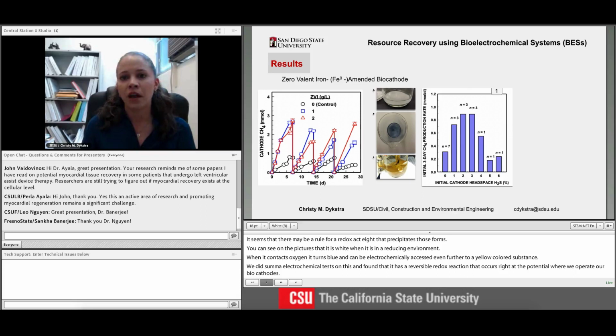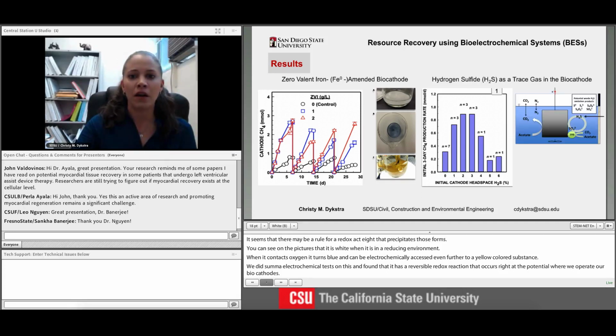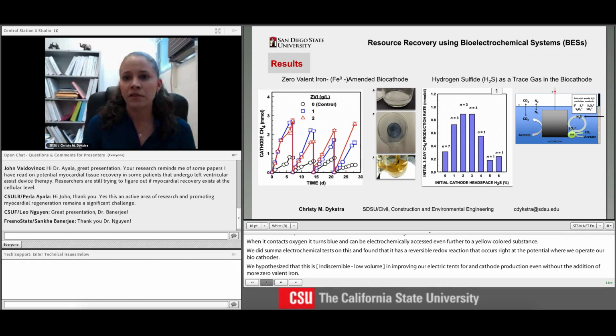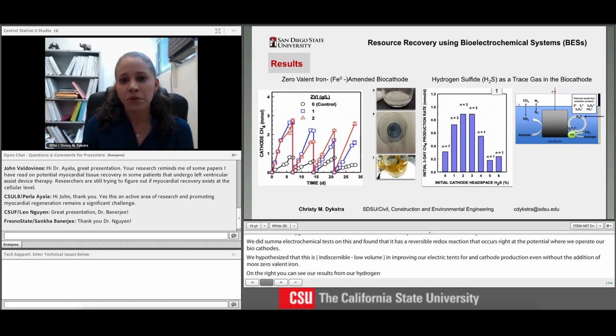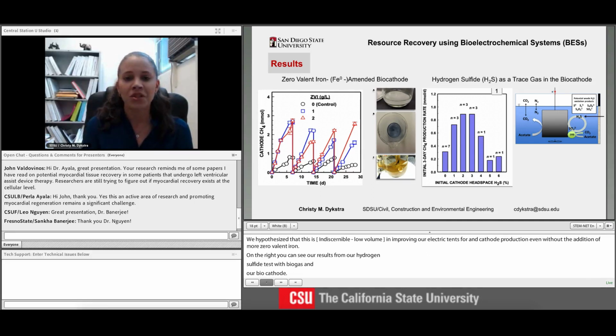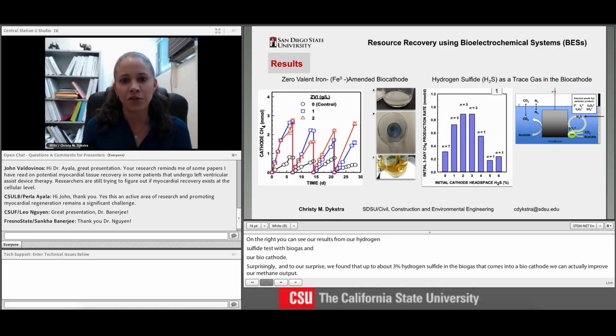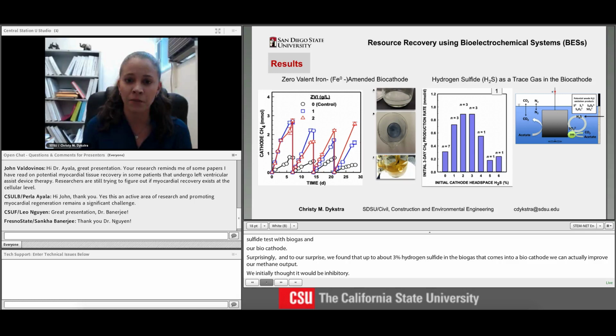On the right, you can see our results from our hydrogen sulfide tests with biogas in our biocathode. To our surprise, we found that up to about 3% hydrogen sulfide in the biogas that comes into a biocathode, we can actually improve our methane output. We initially thought that it would be inhibitory. However, what we find is that the hydrogen sulfide is transported across the membrane from the cathode to the anode, where it is oxidized, improves the current output, and improves our methane output at the end.